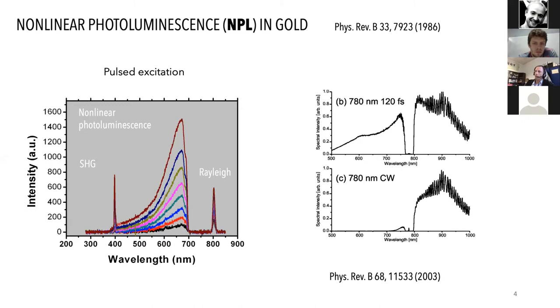So the reason why we don't see much of the light extending towards the blue side of the spectrum is because of interband transitions. The interpretation is that the NPL, which is emitted as a broadband signal here, will start hitting the interband transition for one photon, and the structure or the gold will be reabsorbing basically that emitted power. And this is why it's very inefficient in the blue side of the spectrum. Of course, if you change your material, if you move from gold to silver, you'll be able to extend this nonlinear photoluminescence a little bit higher in the blue side of the spectrum.